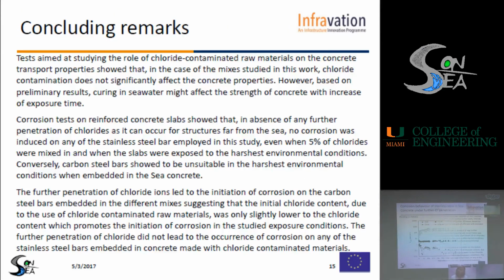So, to conclude, the test aimed at studying the role of chloride-contaminated raw materials on the concrete transport properties showed that in the case of the mixes studied in this work, chloride contamination does not significantly affect the concrete properties. However, based on preliminary results, curing in seawater might affect the strength of concrete with the increase of exposure time.